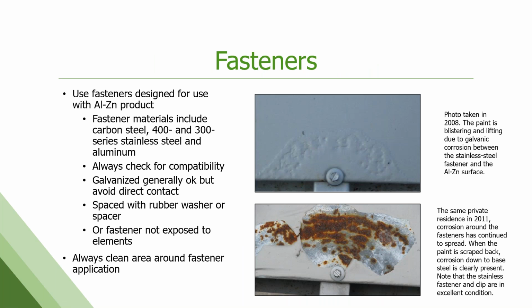Fasteners, very important. Got to use fasteners designed to go with the aluminum-zinc panel. Again, there are technical bulletins and lots of data out there on this and recommendations as to what's best. They can include carbon steel 400 or 300 series stainless in a non-corrosive environment. That's very good. In a corrosive environment, you don't want to use stainless. So you always got to check for compatibility. Galvanized is generally okay, but we try to avoid direct contact. So there are a lot of coated fasteners out there that have either a paint or a polymer coating on them, so you're not getting that direct contact. Want to make sure you're using the right rubber washers and spacers, or a fastener that's not exposed to the elements.